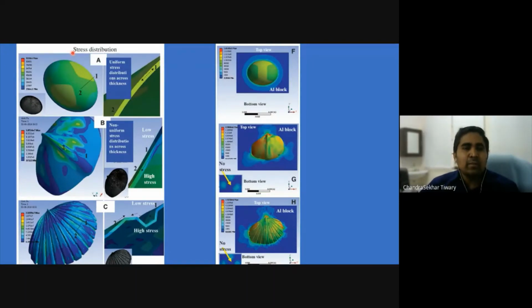What we see is, if you have a spherical structure and you press here, the stress and strain both distribute uniformly. The first complexity in the sea shell structure, which is this kind of spine, results in a complexity in the surface. What we see is, because of this complexity, a stress localization at certain places. What I mean to say is, it's not uniformly distributed. Hence, you can accommodate a lot of stress. And if you add the second level of complexity, it means these ups and downs, a positive and negative curvature, you can see it can take even higher stress levels.